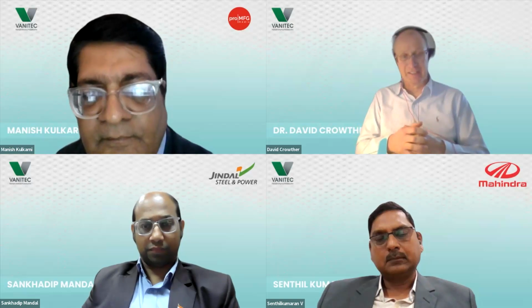Thank you very much, Manish. I'd like to make a few comments and try to draw some different segments together. We've heard on the use of vanadium-containing steels in the automotive sector, and we also touched on the topic of hydrogen embrittlement, in particular related to line pipe. But there is a sort of common ground here. Some automotive steels are produced using a hot forming process, in that a flat strip is heated to around 900, and during the forming process, it's quenched to martensite, a very high strength material. And these types of component are used for things like impact resistance, the B pillars in cars, because they're so strong. One problem you see as you go to higher and higher strengths is that these steels are becoming more susceptible to hydrogen embrittlement.